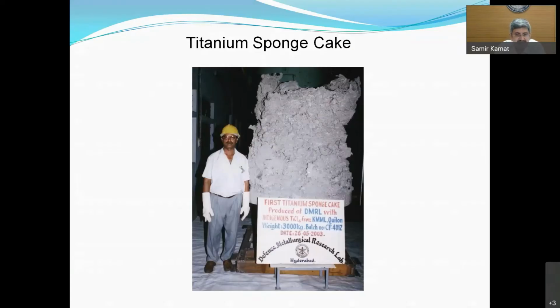So this is the first 3000 kg titanium sponge cake, which was obtained from the DMRL pilot plant. As you can see from the date here, this was established in 2003. Although the technology was established in 2003, there were no takers to set up a full-fledged commercial plant. So from 2003 to 2007, we had a great technology, but no takers to set up a plant.